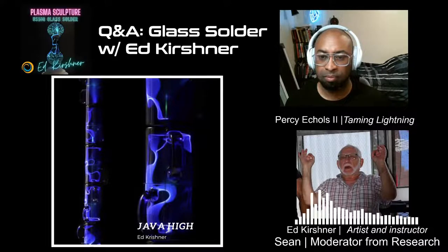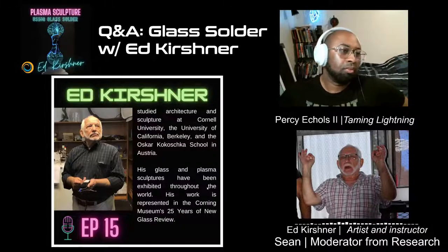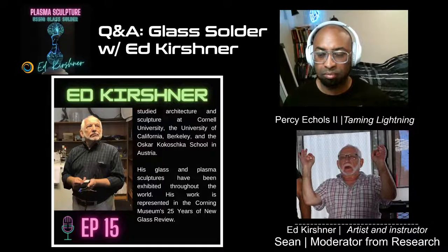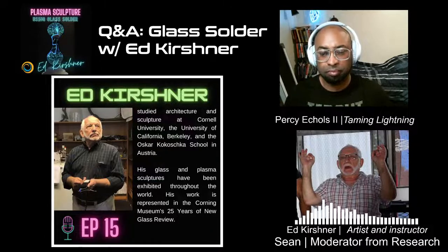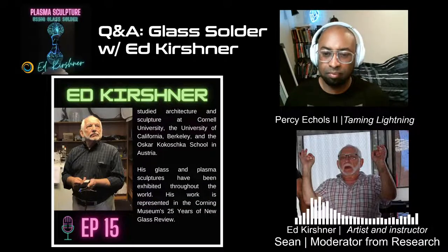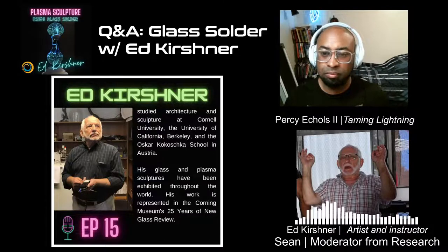With a little effort, we can get an electrode, but the failure rate is somewhat higher. We generally use a transition glass between the electrode and the hard glass, with no guarantee. But you'll also find other glass forms. For example, I've used carafes that have a large bottom insert. In a case like that, you can have an external or capacitive electrode situation, and then you don't need an electrode. You just have to be a little tricky to put the tubulation on, but it's easier to get away with a tubulation than an electrode when there's a somewhat incompatibility.